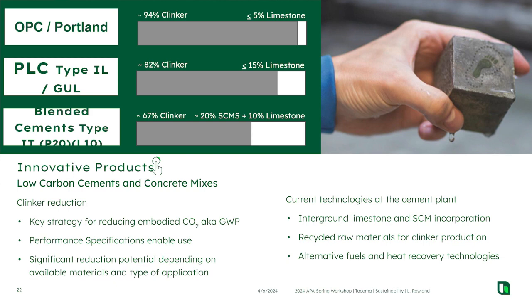On the surface, I've taken calcium hydroxide and reacted it with the CO2 out of the atmosphere and formed new calcium carbonate. Concrete actually gains weight in place. It gets heavier because it's absorbing CO2 right out of the atmosphere. Up to 50% of all the calcining CO2 that I emit in my cement process can be reabsorbed back into the concrete. We want to account for that because, when people are counting carbons and want to point the finger at us, we want to say, hey, by the way, we're also sequestering CO2 right out of the atmosphere with our concrete.